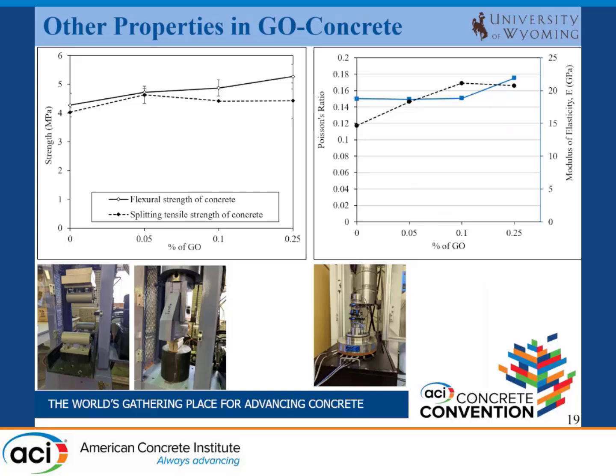Under the curing period of 28 days, we did some other tests in the range of 0 to 0.25% of graphene oxide. We found that the flexural and split tensile strength does not change that much, and did not decrease much compared to the control mix. We also found a similar scenario in the modulus of elasticity and Poisson ratio: it does not change or alter the products.